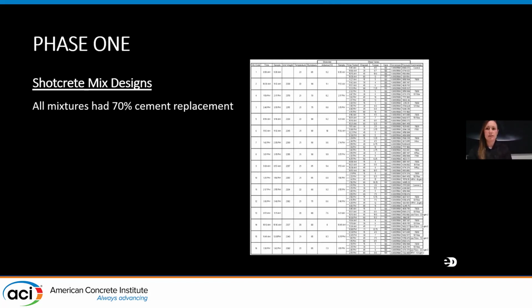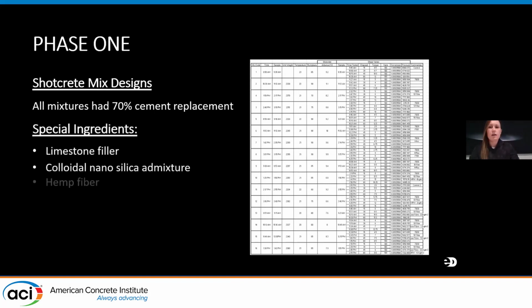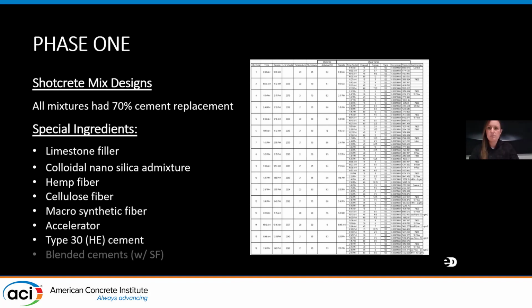So I know you all are waiting for me to spill the magic ingredients for how we got a mix that historically was limited to 20% slag replacement and bring it up to 70%. We had to tackle the stickability and finishability problem that arose from replacing that much cement. So we approached it from 2 angles. 1, by increasing the particle packing, and 2, by introducing a product that was hydrophilic. We tested multiple filler percentages, blended cements, and a colloidal nanosilica admixture, as well as different hemp fiber and cellulose fiber dosages.